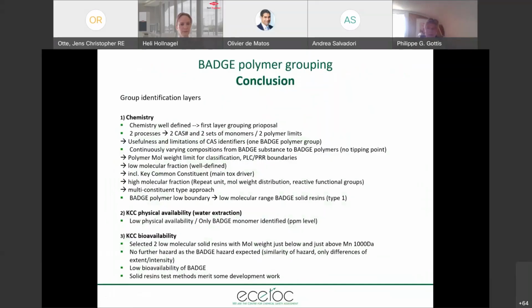So let me please summarize the main takeaway learnings from this case study. Using the analytical and the chemical data, we can work out a first layer grouping proposal. Although BADGE polymers can be obtained via two processes, with two different CAS identifiers, there is enough evidence to make one group. And CAS identifiers are useful, but not sufficient to unambiguously identify polymer groups. The BADGE chemistry produces continuously varying composition from BADGE substance to a wide range of low and high polymers, thus providing a better understanding of the type of hazard to be expected when moving from substances in general to polymers. The analytical data generated allow to assess a PLC/PRR status, and we use a polymer fraction